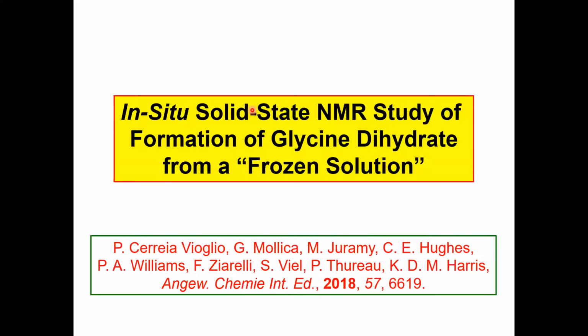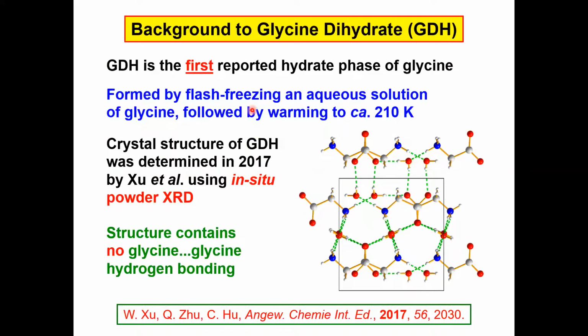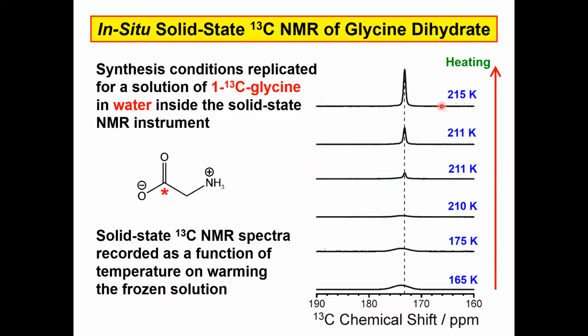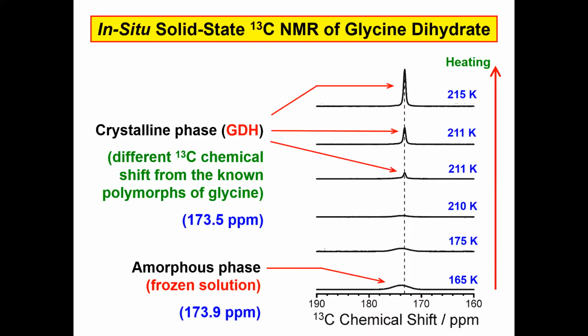Another example where we get crystallization occurring from a frozen solution concerns glycine dihydrate. Now, the first reported hydrate phase of glycine was only published in 2017 by Xu and others in this paper here, and this was obtained by rapid flash freezing of the aqueous solution, followed by warming to a temperature around that value. So we replicated this procedure in the solid-state NMR spectrometer, and indeed, following the rapid quenching, you see a very broad signal corresponding to a frozen solution of glycine in water. But then as we increase temperature to around 210 Kelvin, we see crystallization occurring.